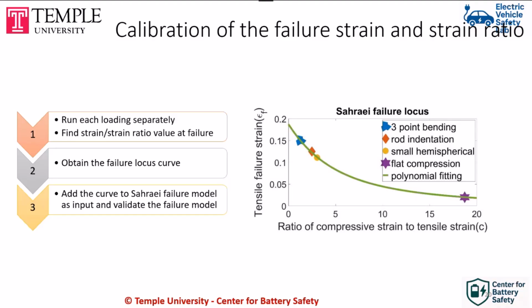tensile strain at failure. So you can see the blue one is the 3-point bending curve. Usually the failure happens on the tensile side, where there is not much compression, so it has the highest failure strain. Then you see the rod indentation, a small hemispherical punch, and at the end you see the pure compression